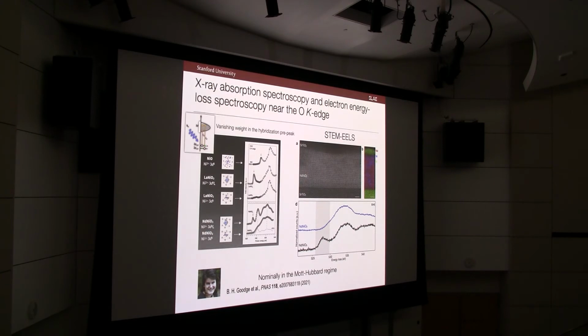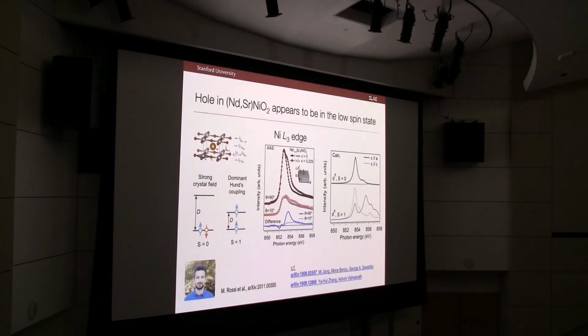And so this is by X-rays. By electron energy loss spectra, you have access to rather similar features. This is looking at the oxygen K edge regime laterally through a cross-sectional TEM sample. And again, the same story: in the perovskite phase, you have this pre-peak that is absent in the planar nickelate. And so at the nominal level, the conclusion of these sorts of studies is that we're in the so-called Mott-Hubbard regime, which is a little bit weird for this side of the periodic table, but again, we have this very low oxidation state for nickel.